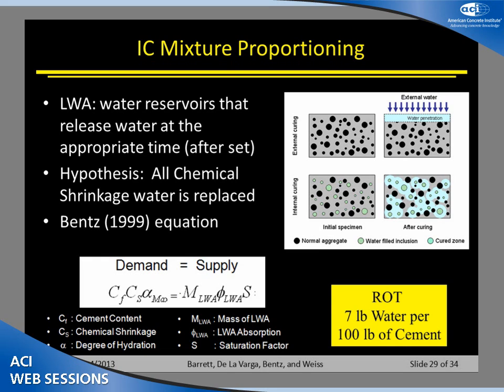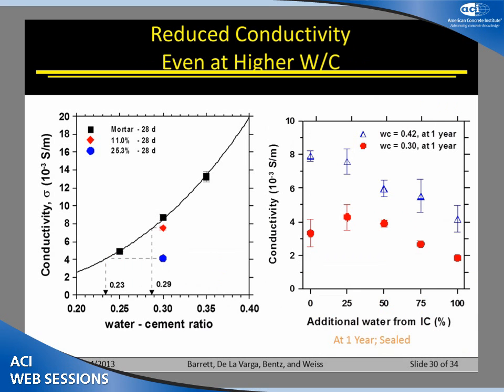So the idea is when water is needed, it's pulled out of the lightweight aggregates, it's available throughout the cross-section to hydrate the overall cement. And there's a quick calculation that you can do to calculate how much water you need. It turns out that you need about 7 pounds of water for every 100 pounds of cementitious materials you've got in the overall system.